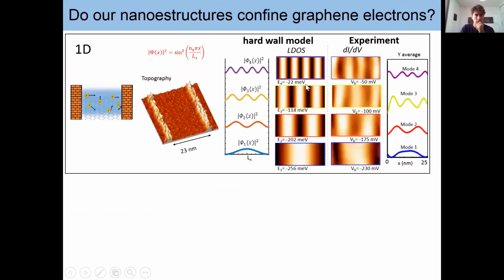So the question is now, do those nanostructures confine graphene electrons? To answer this question, we first did some QPI measurements. Here you see a one-dimensional resonator, and then we analyzed the results using a very simple hard-wall model, so infinite barriers. So those are the eigenmodes that we expect to see for such a one-dimensional model, and this is the result of our experiments where we very nicely see the different modes. The first 4 modes we can very nicely see.